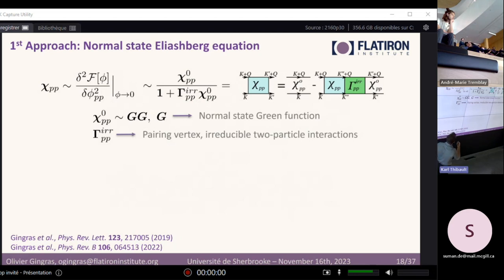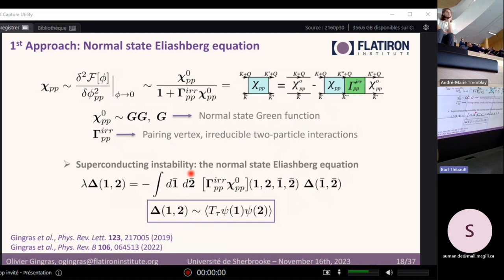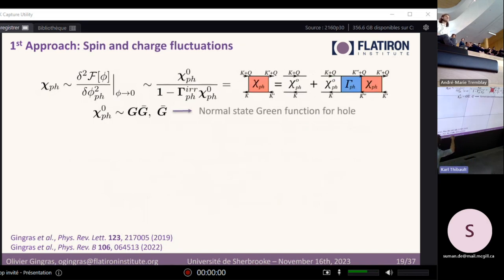And so we can look at when this susceptibility diverges. It is the same thing as looking at when this operator here has an eigenvalue of minus one. So basically, this is the Eliashberg equation. We construct this operator and solve the eigenvalue problem. We look at the largest eigenvalue, and the corresponding eigenvector can be studied to analyze what symmetries it transforms like, and this gives us candidates for the possible superconducting symmetries. Now, the problem here is actually constructing this operator. So how do we do that? Basically, we go to a similar formalism where we look at the particle-hole susceptibility, which has a very similar way of being expanded in terms of diagrams.